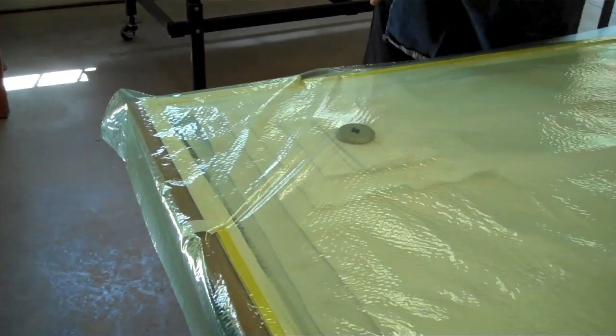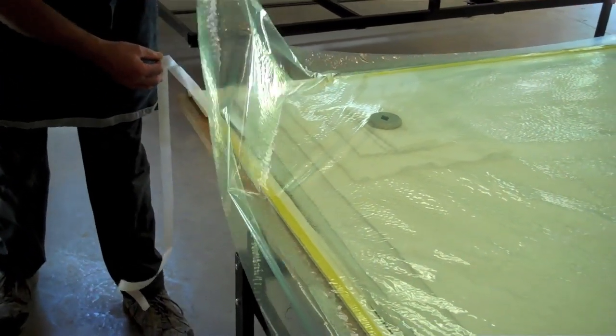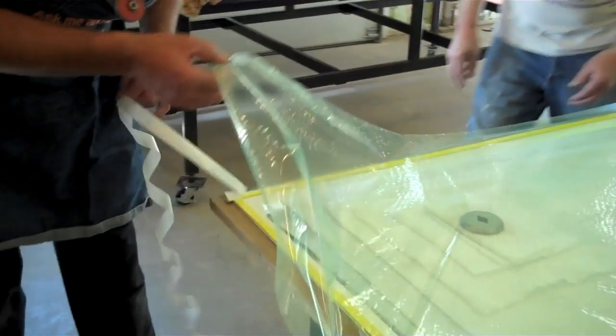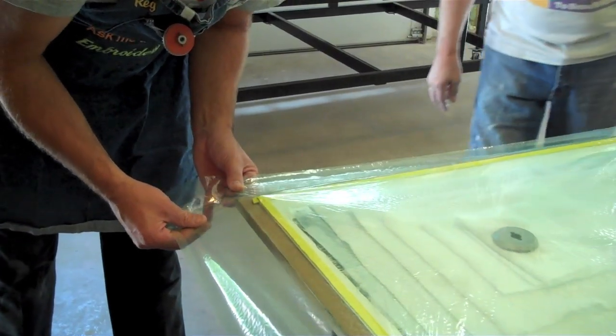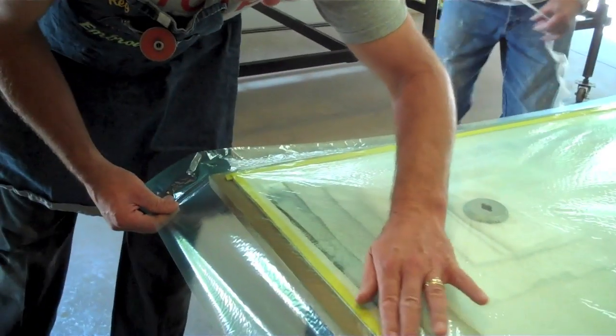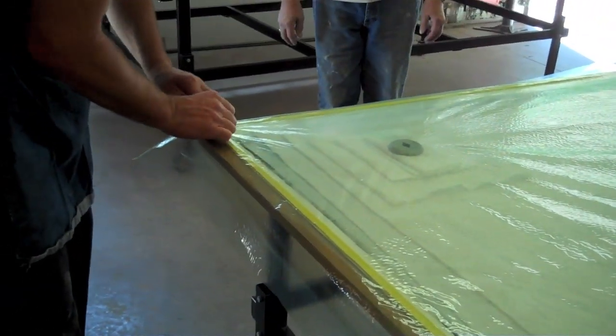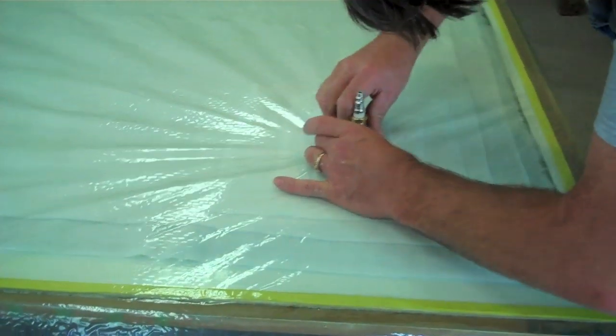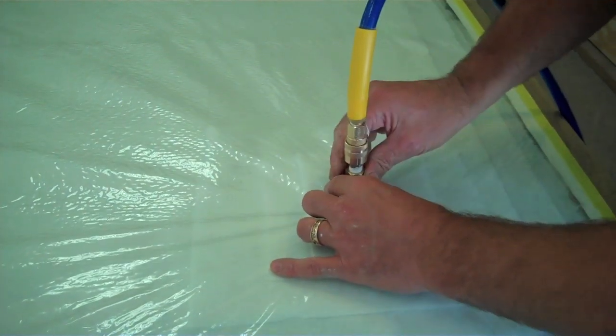Rubs it down tight so we get a good seal. And you can see the head of the puck here is sealed under the plastic for right now. I'm guessing we just kind of shove the other end through poking a hole in the plastic. It's pretty close. But we may cut a little notch or something first. I'm going to use a number nine single edge razor blade for a little sliver. He's making sure that there's no fibers stuck to the yellow mastic. Otherwise it'll suck air through. You won't get a good vacuum.